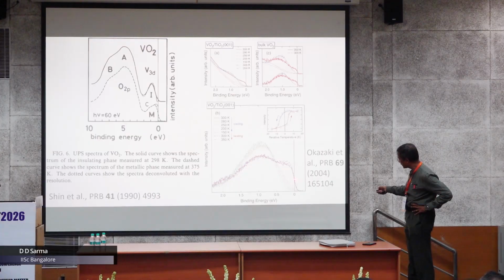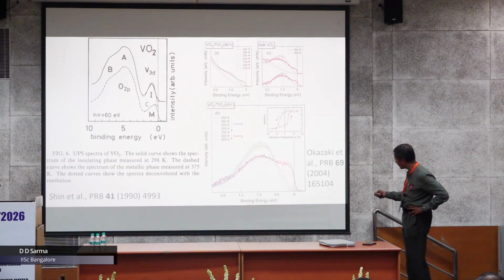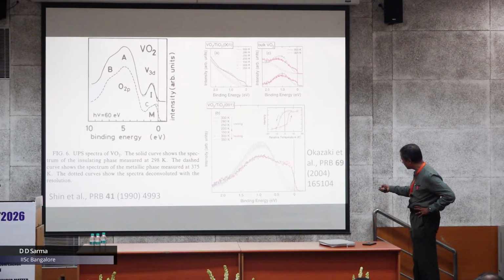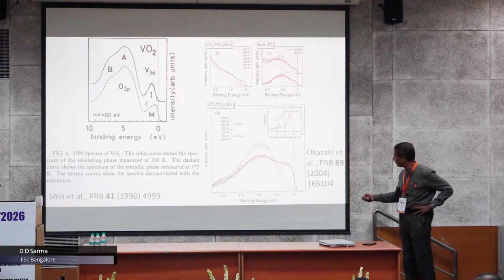And as you lower the temperature, suddenly at a temperature, it makes this transition. The spectral weight qualitatively changes from this large intensity at the Fermi energy to almost no intensity at the Fermi energy, signifying an insulator. But the point that everybody drew attention to, that besides these states which characterize it as a metal, there's a large weight far down away from the chemical potential which mimics the insulating spectral weight, and that must come from correlation effect, even for the metallic state.